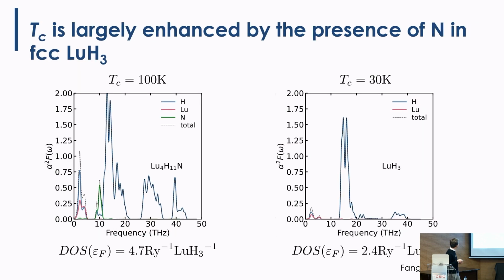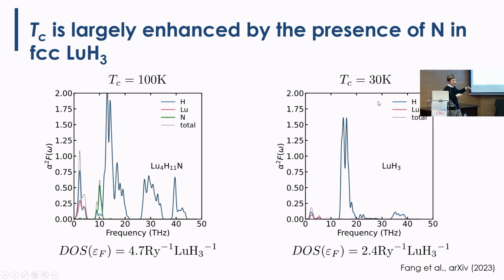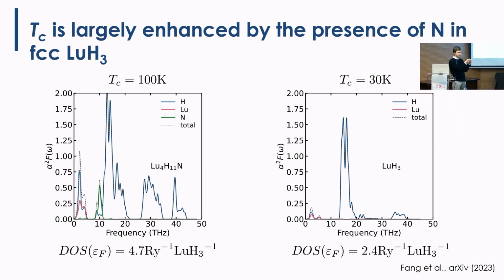And the interesting thing is that if we compare, this is very similar to lutetium H3, okay? Which has a much lower TC. So here we are substituting out of 4 hydrogens in the octahedral side, 1 nitrogen. And we get a TC increase of a factor of 3. So still, this is very low from the experiment, right? It's a much, much lower critical temperature. It's not dynamically stable in our calculations at ambient pressure. It's not thermodynamically stable. But there is something.